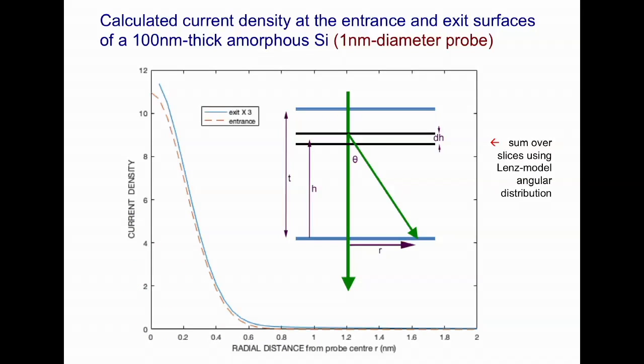In the case of a thin amorphous specimen, it's easy to calculate the beam broadening at a particular plane by summing over the elastic scattering that occurred at previous planes. The resulting blue curve on the left shows the current density after a sub-nanometer beam of 100 kilovolt electrons has traveled 100 nanometers into a silicon specimen, plotted against distance from the center of the probe. At first sight, this doesn't look much different from the dashed red curve, which is the current density profile at the entrance surface, except for a small tail that extends to larger radius.